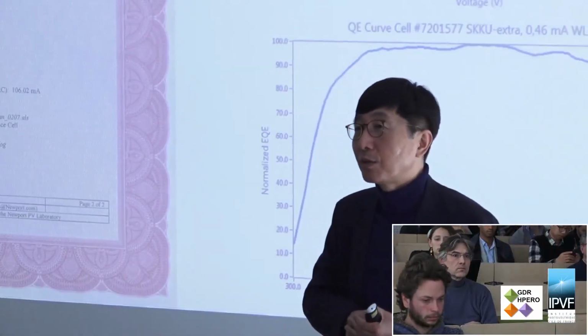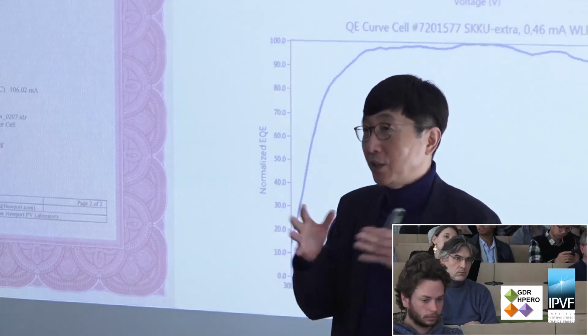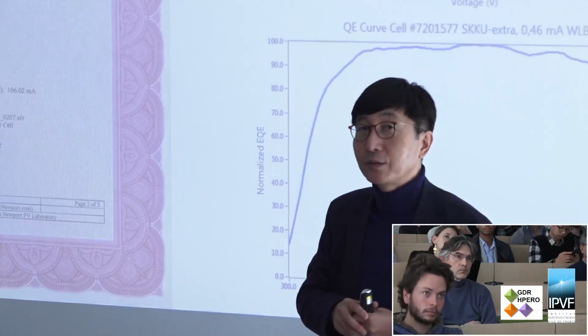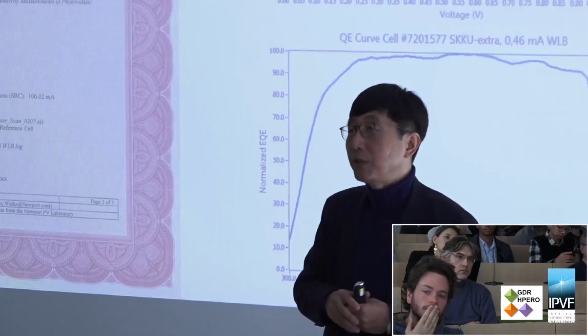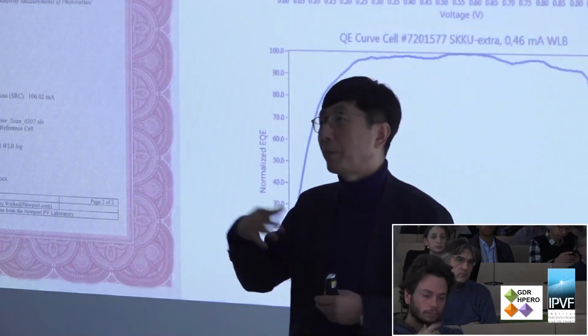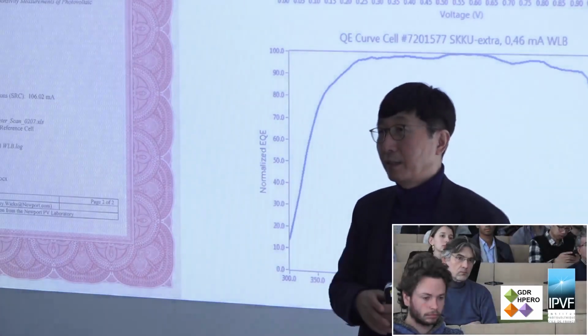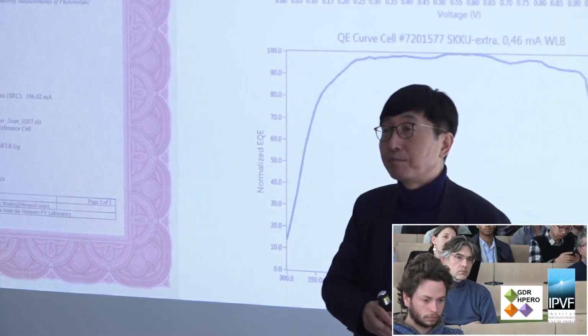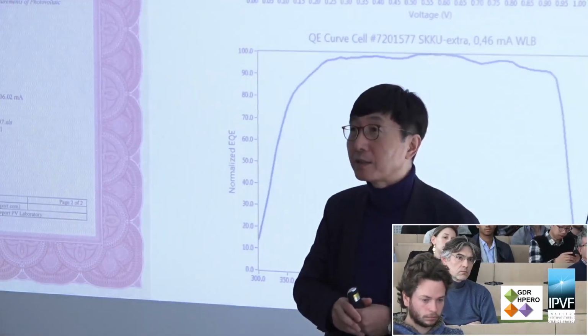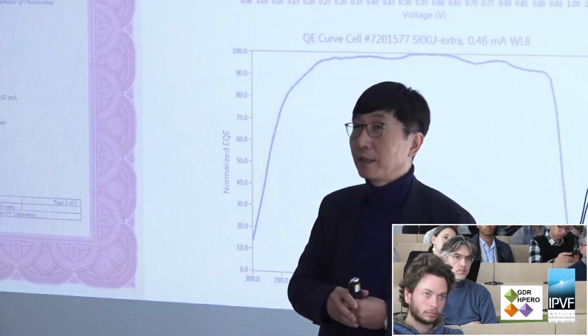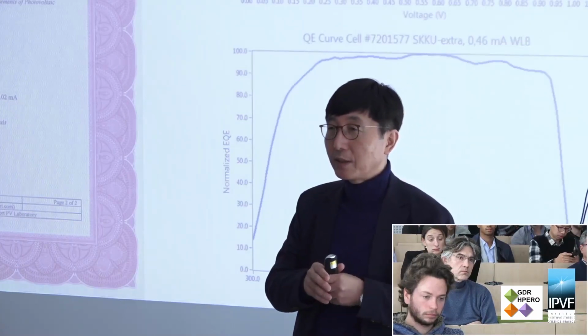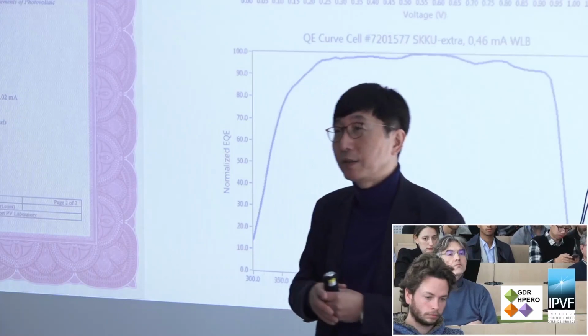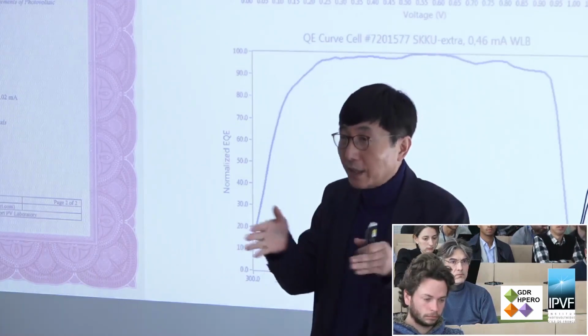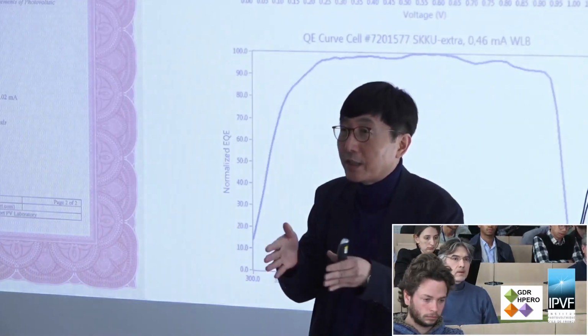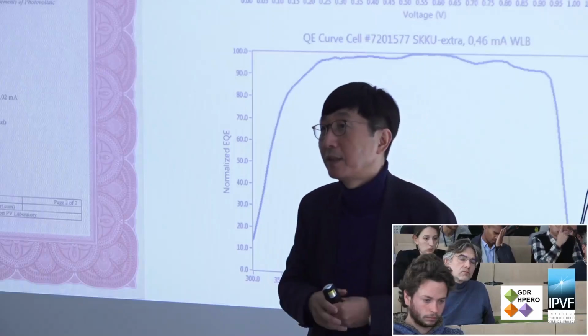We actually observe the lattice contraction. It reduces the lattice constant. Therefore, a very tiny amount of cesium ion stabilizes the A site, and therefore the FA ion. In terms of interaction, the methylammonium cation or the formamidinium cation interacts less with the iodide in the perovskite structure. The FA is less stable than the MA cation because of the lower dipole moment. And if you have this small amount of cesium ion, then the lattice constant decreased. Therefore, we stabilized the FA ion at the A site. Yes.